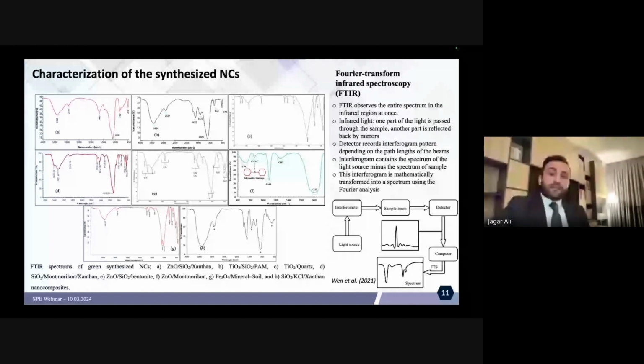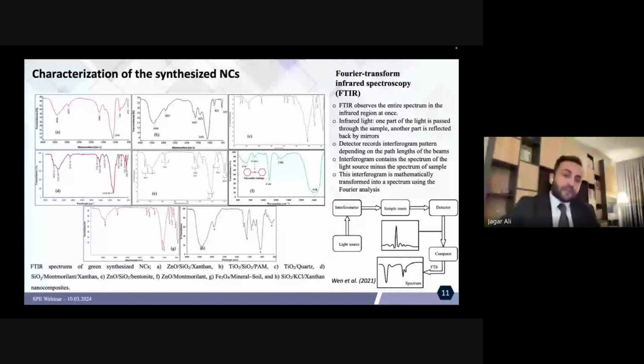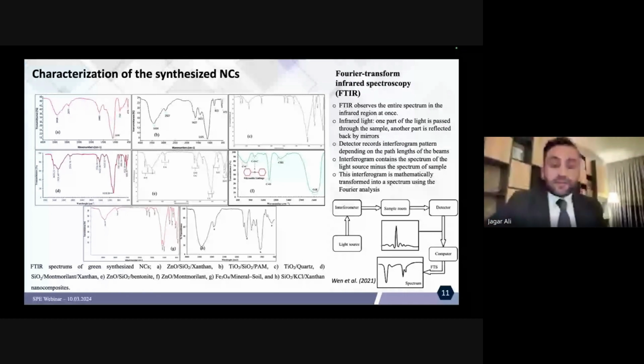And then we have FTIR. Also, we use this technique in order to estimate the functionality of the nanocomposite that we have. For example, here we have 8 spectrums of FTIR for 8 nanocomposites that we prepared. So here also we have a correlation table of different functional groups. For example, phenolic. For example, we have alkaline, acidic, base functional groups. So with having these spectrums and comparing with the correlation tables that we have internationally, based on the standards, you can confirm the fabrication of the nanocomposite that we have.